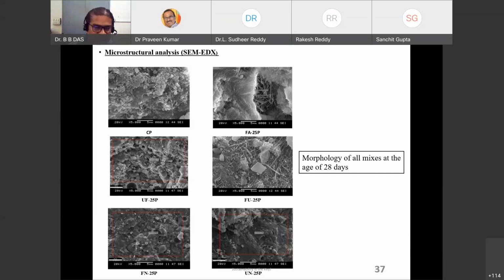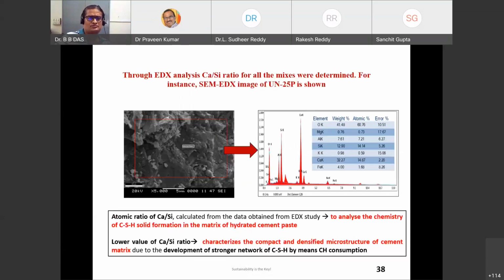Because this is done in secondary electron mode, it will just give me the surface morphology. If you really want to go into quantification studies, remember you have to integrate your SEM with EDX. EDX is going to give the elemental analysis. Based on the elemental analysis, we determined the calcium to silica ratio. Calcium is an ion and silica is another ion. We know both ions are very important for a cementitious composite. Let us compare the atomic ratio of calcium by silica.